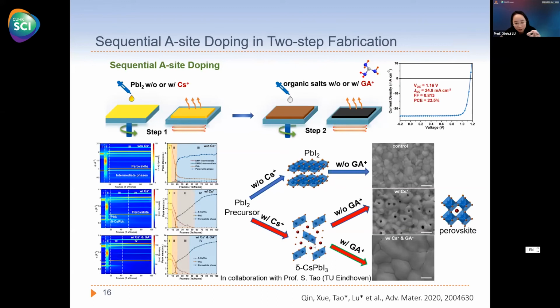small scarce nucleation centers of delta cesium lead iodide phase. So the formation of perovskite prefers to start with this delta phase, which will significantly increase the grain size. However, in the second step, without the doping of GA, the large cation, the crystallization speed is relatively slow, which will lead to pinholes in the film. So this is no good. With the doping, we can promote the crystallization in the second step and form this pinhole-free and larger grain size perovskite film, which leads to a very good device.